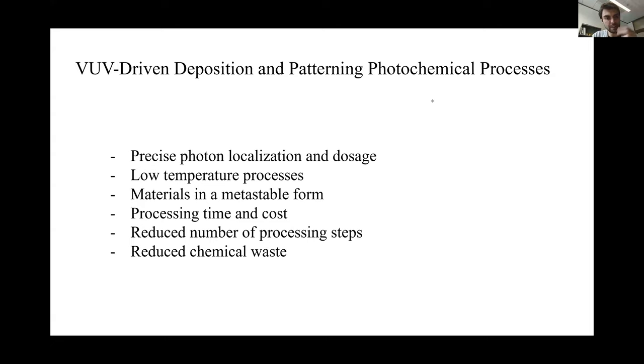So the main advantages would be precise localization and control of dosage of VUV. So you can precisely control chemical reactions in specific places of your wafer if desired. This is a low temperature process, may be done at room temperature, maybe done at a bit higher temperatures, but still this is superior to all other processes. This helps to keep your thermal budget really, really low. This also allows you to deposit SiO2 and other oxides on polymers, which may actually be used for optical interconnects in the future.